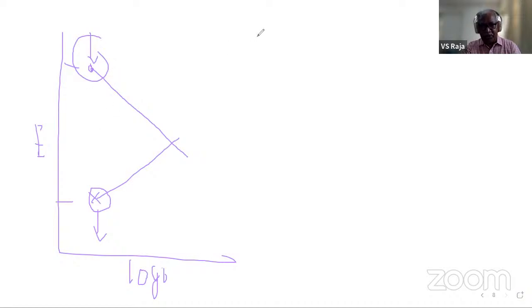Now, what happens now? Because they have two different potentials. Now, see, these are on the same metal. You have metal oxidation here, equilibrium, and you have hydrogen equilibrium. The metal is now conducting. See, at one place it becomes zero, for example here 0, suppose for hydrogen, but iron is going to be minus 0.44. Please see that it may establish two potentials on the same metal surface. The metal surface is conducting now. There's no resistance here. So this voltage will drift. This will drift towards this. When this drifts, this follows this kinetics. This follows this kinetics. And at this particular point, it's a very important point, the rate of reduction of hydrogen equals the rate of oxidation of the metal here.